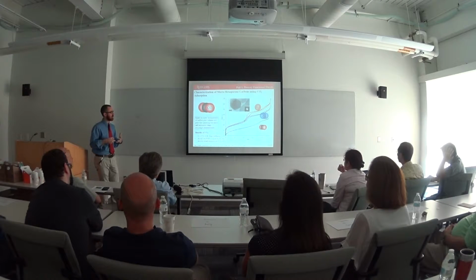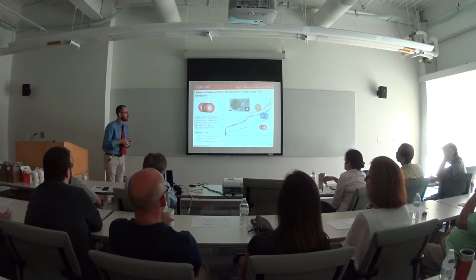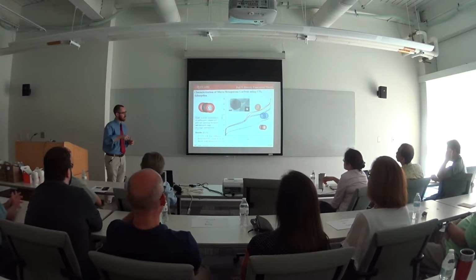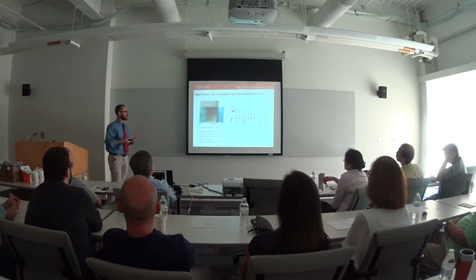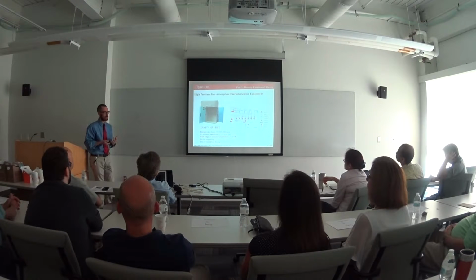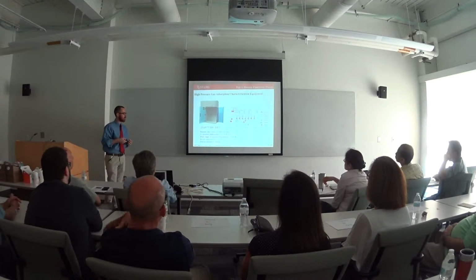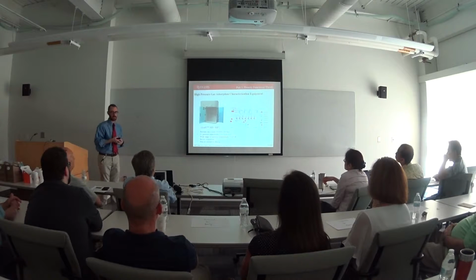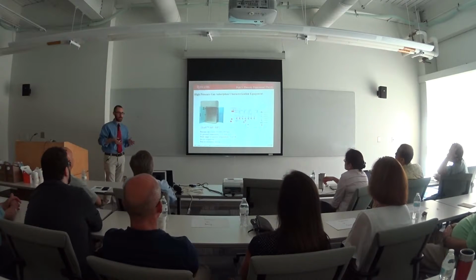And what I did in this portion of my dissertation was to extend the relative pressure range of our CO2 adsorption all the way up to the saturation pressure of CO2. This allows us to compare the entire isotherm of nitrogen and argon to CO2, so that we can also capture mesopores as well as the micropores. In order to do this, we need to use something called high pressure gas adsorption, and there are only very few instruments that are capable of doing this. For example, this particular instrument, which was used for the CO2 analysis, can reach pressures of over 35 bar. For reference, atmospheric pressure is approximately 1 bar, so this is very high pressure.